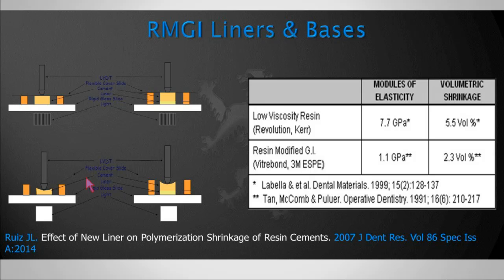Then to see what an elastic liner can do, we placed a 0.5 millimeter increment of resin modified glass ionomer material, and then cured that. We cured the liner, and on top of that we put a 2 millimeter increment of composite and cured the composite. What we noticed is the deflection was about 50% of the deflection that we had without the liner, which shows that flexibility matters, because if you look at the study from Labella, resin modified glass ionomers are 7 times more elastic than resin, which means they're considerably more forgiving to the effects of polymerization shrinkage. So that's the benefit of a liner.